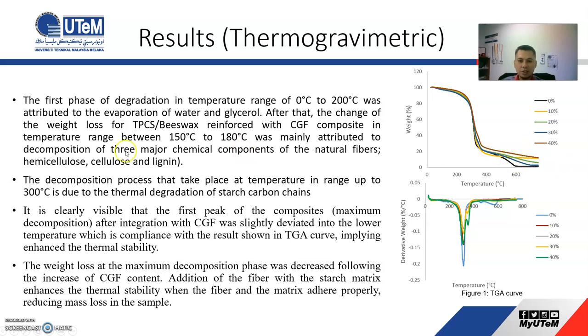Okay, so let's see what the information given. So the first phase of degradation, the temperature from 0 to 200, this region is normally attributed to evaporation of water and glycerol. And after that the weight loss at about 150 to 180 is mainly attributed to the decomposition of three major chemical components, such as hemicellulose, cellulose, and lignin for the natural fiber. And then for the temperature up to 300, it's due to the thermal degradation of starch carbon chains. So it's around the peak here.